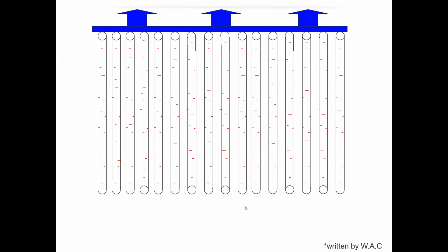I would like to talk about this topic. So this is an animation of unidirectional failure made by Professor Bill Curtin. The red dashed line represents a defect. So it breaks as load increases. At a certain point, the critical cluster occurs, and this cluster propagates like a crack, eventually resulting in the final failure.